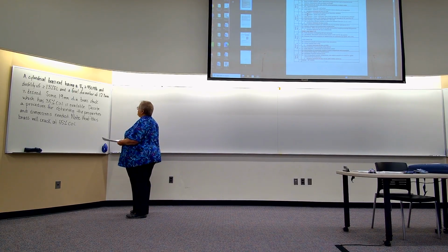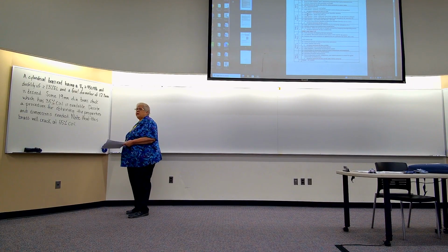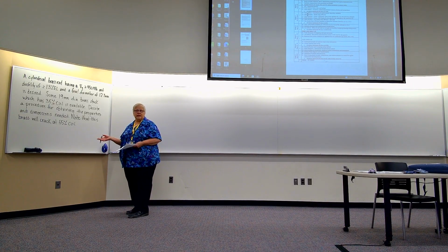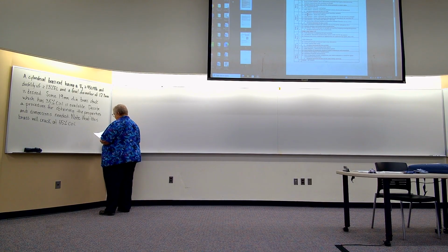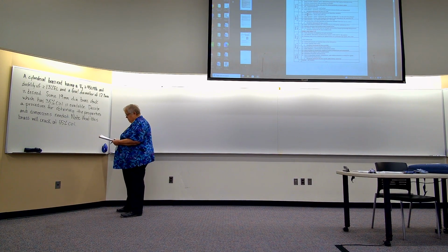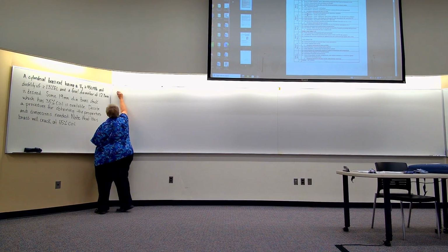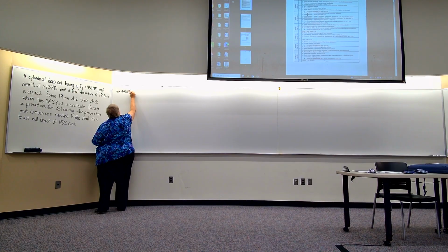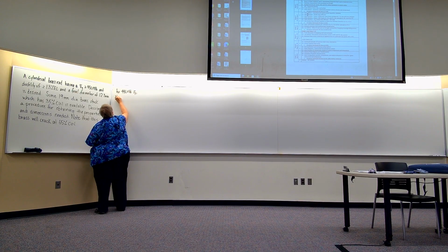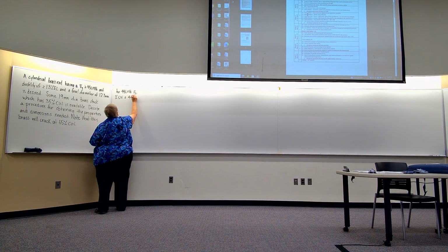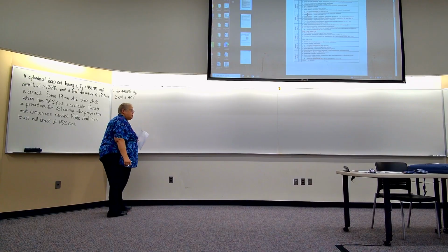So I would say my best first step: I know what my final properties are, so I can figure out how much cold work I want in the very last step in order to get those properties. If you still have your homework or the image of strength and ductility versus percent cold work, then for brass, I want 450 megapascals yield strength. That looks to me to be about 40% cold work. Percent cold work has to be greater than or equal to 40%. Got that from the graph.